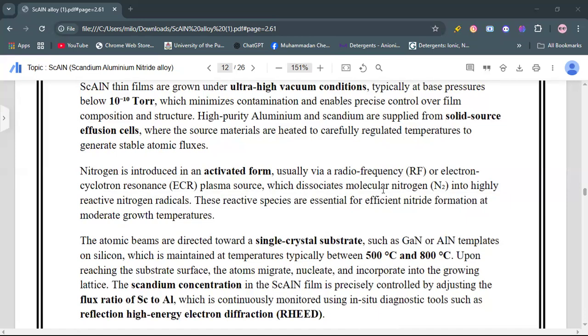are essential for efficient nitride formation at moderate growth temperatures. The atomic beams are directed toward the single crystal substrate, such as gallium nitride or aluminum nitride templates on silicon, which is maintained at a temperature between 500 degrees Celsius and 800 degrees Celsius. Upon reaching the substrate surface, the atoms migrate, nucleate, and incorporate into the growing lattice. The scandium concentration is precisely controlled by adjusting the flux ratio of scandium to aluminum, which is continuously monitored using in situ diagnostic tools such as reflection high energy electron diffraction.